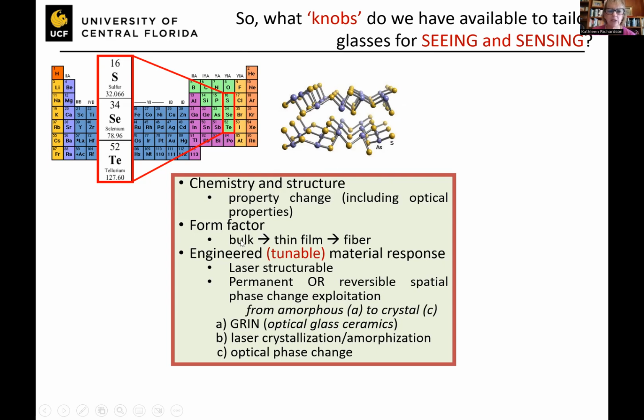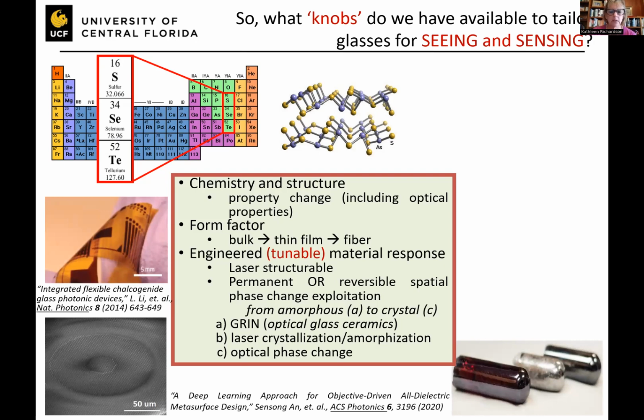and the low temperature aspects of these glasses allow us to very easily switch from bulk materials to thin film materials to fibers, because they are very amenable to shaping in a variety of forms, what I call form factors. And then the other thing that many people who don't know think of as a limitation, these materials can be made tunable. And what do I mean by tunable? It means that we can engineer into the composition attributes which make them amenable to modification, whether that means deposition into thin films, whether it makes them amenable to optical phase change, which I alluded to, which is the ability to change from its amorphous state to its crystalline state and then back again by use of some stimulus.